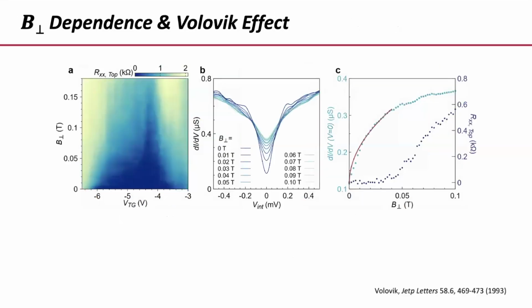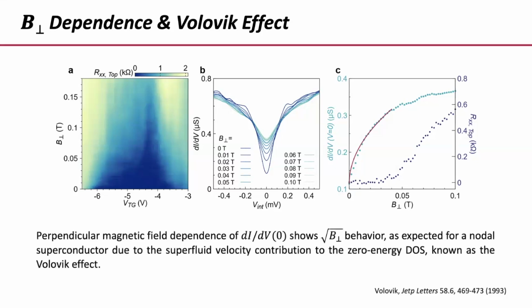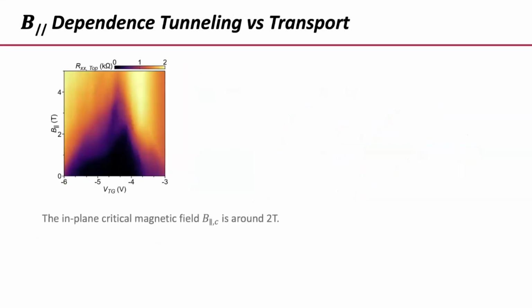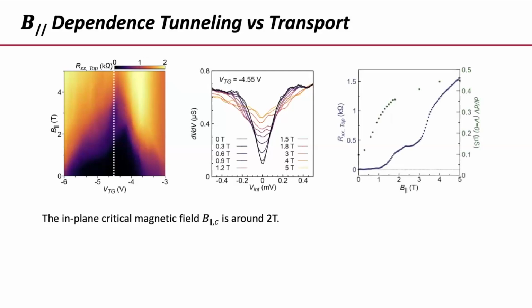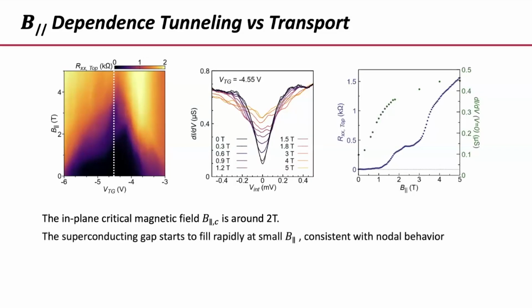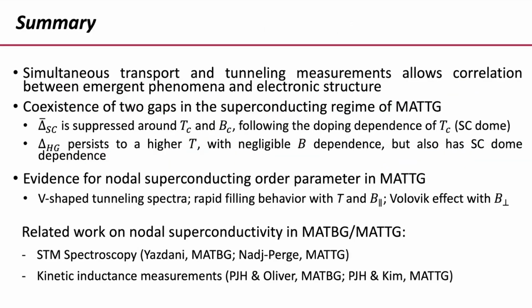Okay? And with this, let me just show you that there is this Volovik effect, which is also a rapid increase of the tunneling density of states when you apply a perpendicular magnetic field. Again, this only appears for nodal superconductors. And in-plane magnetic field dependence also shows this rapid increase, which is again consistent with nodal superconductivity. So with this, I'll skip the summary, okay?